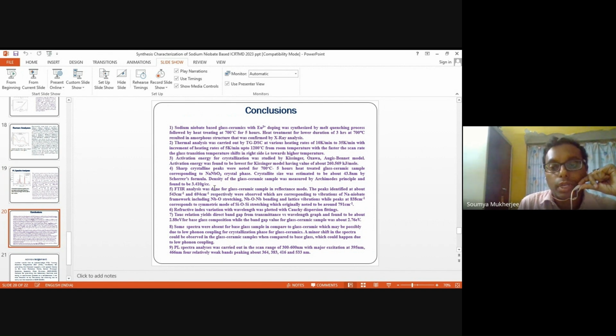FTIR analysis by reflectance mode, where we are getting the metal oxygen bondings. Refractive index is plotted with the Cauchy dispersion fittings. Band gap using the Tauc relationship is 2.88 electron volt for base glass, while the 2.76 value is for glass ceramics. This is in the semiconductor range. And the PL spectra is quite intense for the glass ceramic sample, while it is quite weak in the case of base glass.